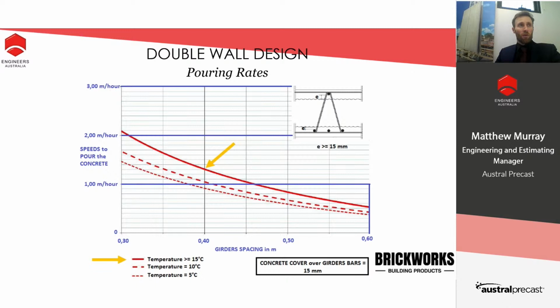From our perspective, it's more reliable just to rely purely on the minimum of 15 and the spacing, which is easier for design and construction, and also making sure that the concreter and the contractor on site are aware of the variation caused by temperature on the hydrostatic nature of concrete. Essentially, the colder the concrete is, the higher the pressure that it will provide, as it will stay hydrostatic for longer compared to when it's above 15 degrees Celsius.